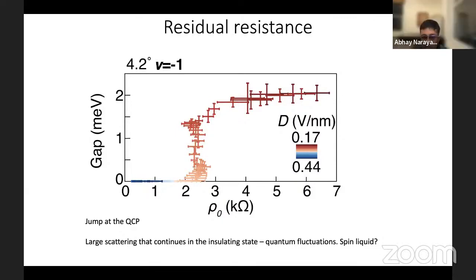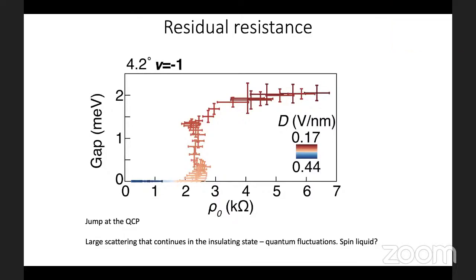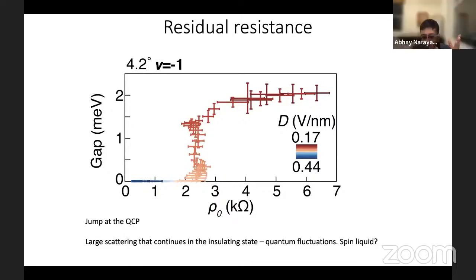Yeah, so in these systems, the spin-orbit coupling basically freezes the spin out of plane. One of the consequences of this, for example, is if you apply an in-plane magnetic field, which you might like to do to introduce some Zeeman effect into the system, it's more or less useless, because you can think of the spin-orbit field as basically having a zero g factor for fields in the plane. So it's fairly simple, it just makes the spin stay out of plane.